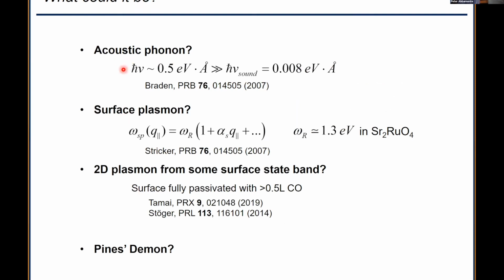So what could it be? You might guess that it could be an acoustic phonon, but if you look at the velocity of the thing, it's around 0.5 eV angstrom. The sound velocity, which is the velocity of the acoustic phonons, is about a factor of 100 times smaller than that. So this thing cannot be a lattice excitation. It's way too fast. It's got to be something electronic.